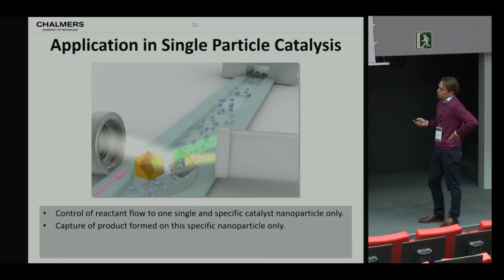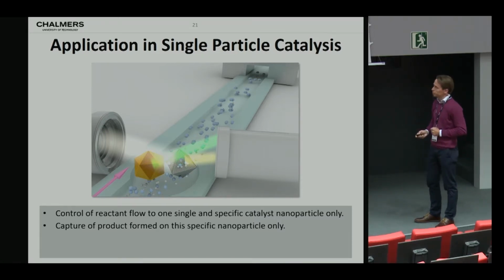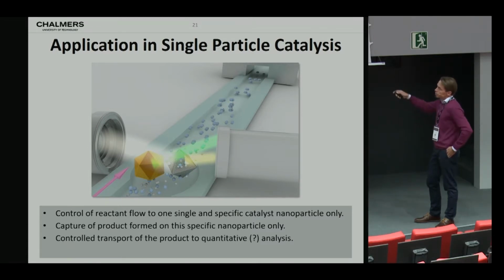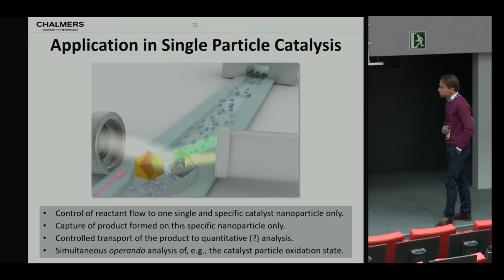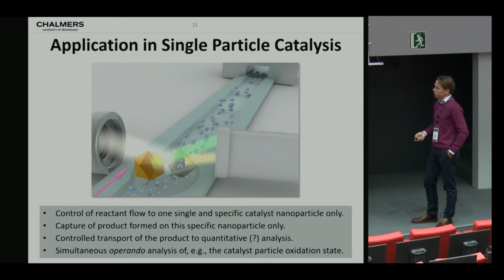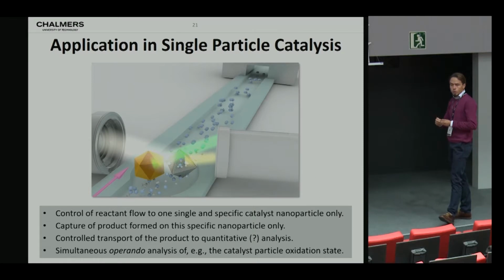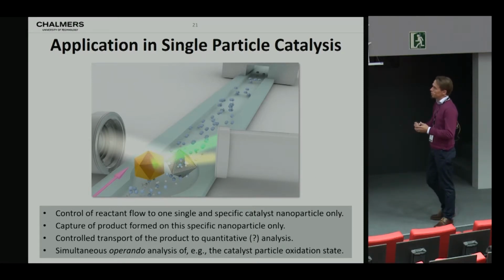Now, very importantly, we are not only controlling the mass transport to the nanoparticle, but also we can collect any product that is formed on this specific nanoparticle only, making sure that the product is not diluted in 3 dimensions, and for that reason becoming even harder to detect. So the question is, does this collection of the products from a single nanoparticle allow us to eventually quantitatively analyze it somewhere downstream? And use the plasmonic fingerprint of our catalyst particle, for example, to in operando measure the oxidation state of the particle as reaction happens, or a change in its geometry due to a surface reconstruction, and so forth. So this is the idea.